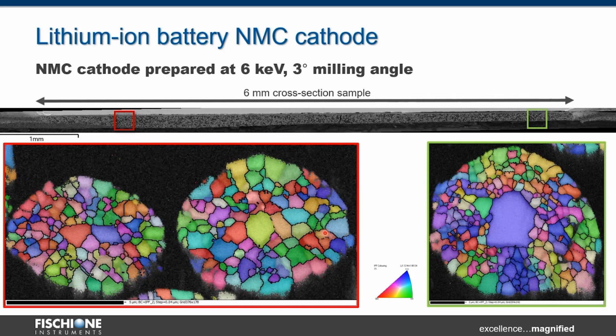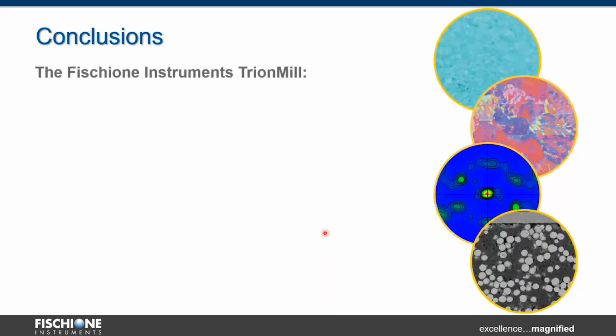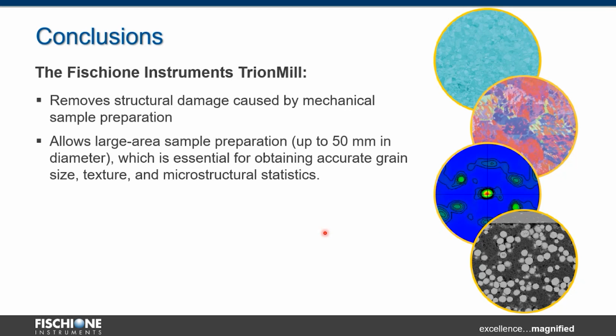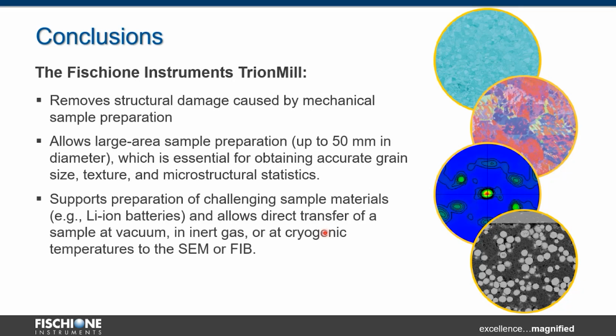With that example, I will finish my presentation and move to the conclusions. I hope I showed here that the Fischione Instruments TrionMill allows you to remove structural damage from mechanical sample preparation and beyond, also FIB and other techniques. It allows large area sample preparation up to 50 millimeters in diameter, which is essential for obtaining accurate grain size, texture, and all the statistical measurements that you wish from your samples. It also supports preparation of challenging sample materials like lithium-ion batteries, and allows direct transfer of a sample under vacuum, in inert gas or cryogenic conditions.